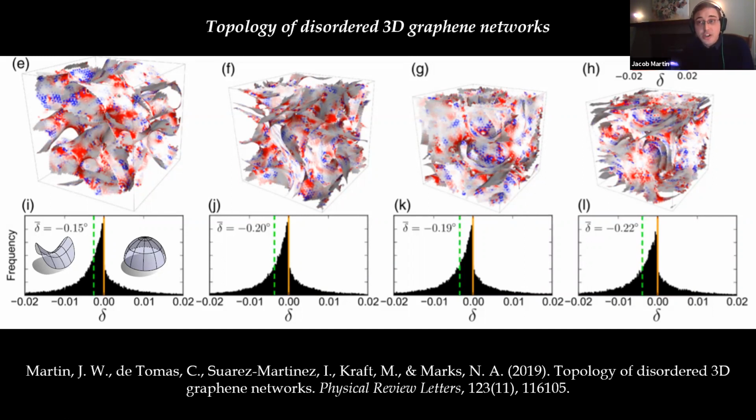Now, what's quite interesting about this is that this is a feature of minimal surfaces. So surfaces that are foam-like. And these are highly stable structures. And they're connected in 3 dimensions. And we think that this is the origin of their high reluctance to convert into graphite, because they would need to break a lot of bonds in 1 dimension. And that foam structure is just so stable.